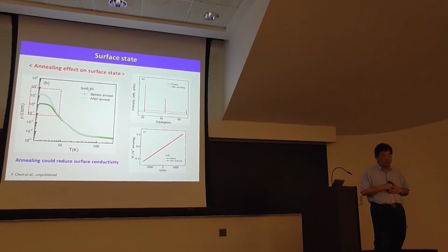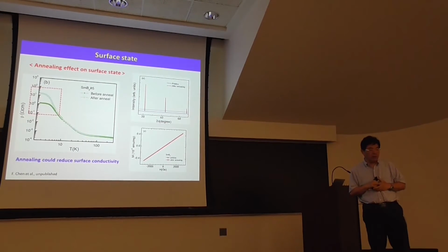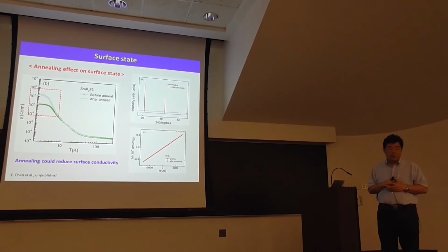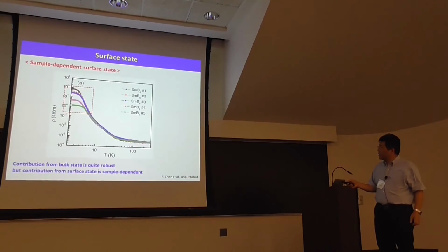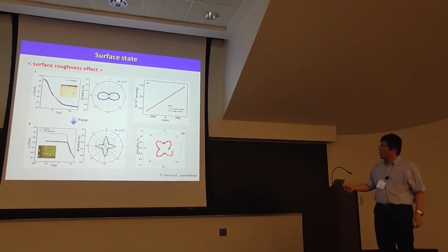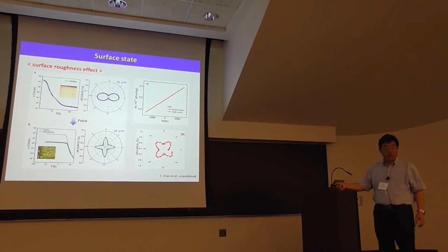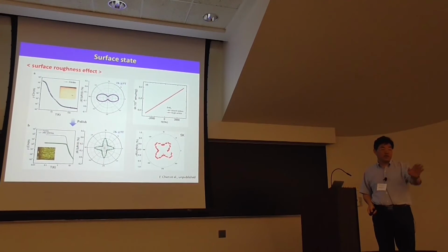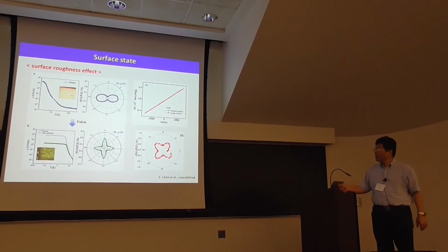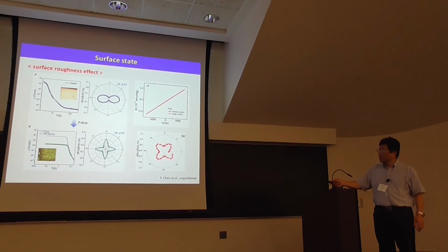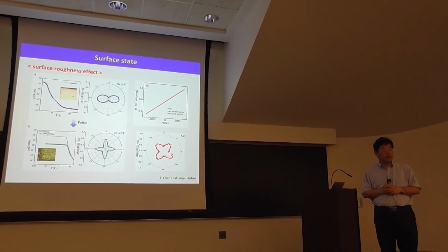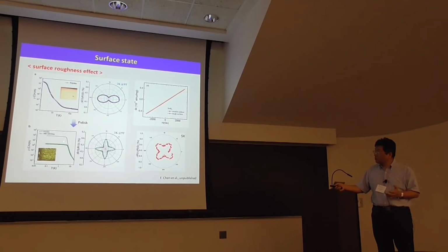And if you do the opposite? If you damage the surface, does it go back? This is damage to this surface. We just use the sandpaper, it's just the polished sample. Then the measurement you can see the behavior is the same. All the above the 4 Kelvin data is the exact superposition, but just below is for the surface state. I don't know why.